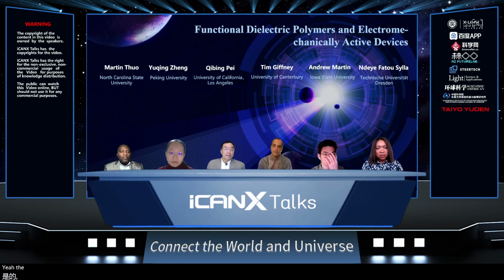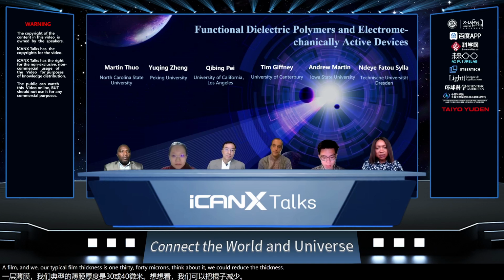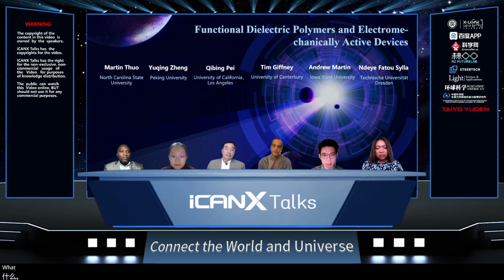And this could be done in two different approaches. One is simply to reduce the thickness of the polymer film. Our typical film thickness is around 30-40 microns. Think about it: if you reduce the thickness to 3 to 4 microns, then your voltage drops to 200-400 volts. The physics doesn't change much, but the challenge is to fabricate thinner films at a high yield. That's not easy. At least at a laboratory scale, it's not simple.